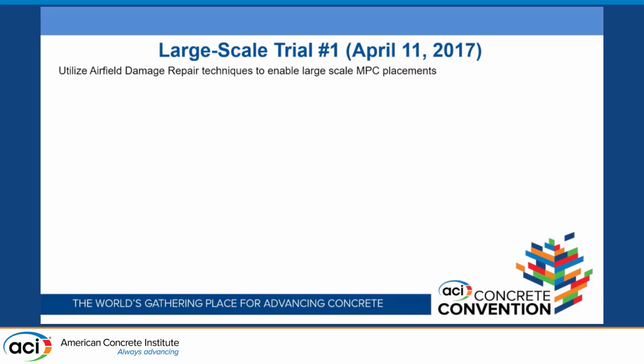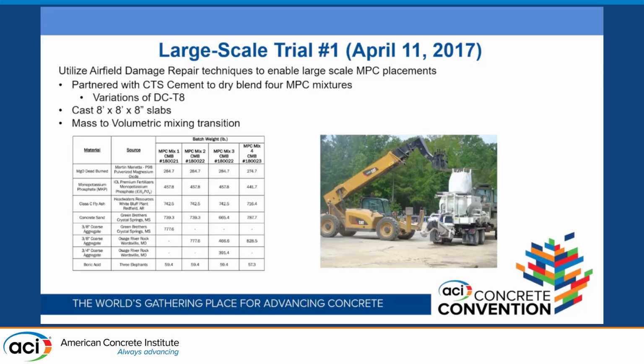It is to utilize airfield damage repair techniques to enable large-scale MPC placement. So what you're going to see on the screen, I'm going to talk about it first, is a simplified volumetric mixer. So it's simplified in that it only has one material hopper in it. All the material that goes into it is pre-blended, and then there's a water tank on the side of it. There's a conveyor belt that pushes your material towards your auger on the back. There's also a water spigot that's feeding the water in at the same time, and all the mixing is done in the auger itself before it's discharged. And that's just a way to get you more working time with a rapid setting material.